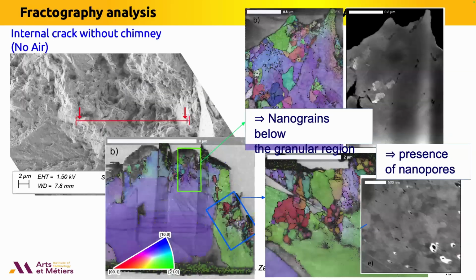If we look just around the facet in the rough area, we have observed the microstructure by EBSD, and we observe nanograins below the granular region. That is also classic, but we also observe, surprisingly, some nanopores. You can see the nanopores here. The scale is very small. So we have both nanograins and nanopores without air.